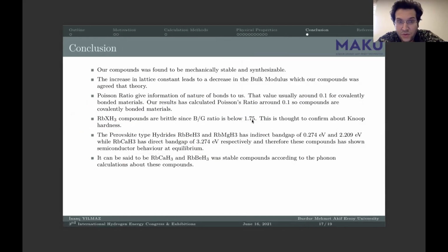Conclusion: our compounds were found to be mechanically stable and synthesizable. The increased lattice constants lead to a decrease in the bulk modulus, which our compounds agreed with theory. Poisson's ratio gives us information on the nature of bonding. That value is usually around 0.1 for covalently bonded materials. Our results have a calculated Poisson's ratio around 0.1, so the compounds are covalently bonded materials.